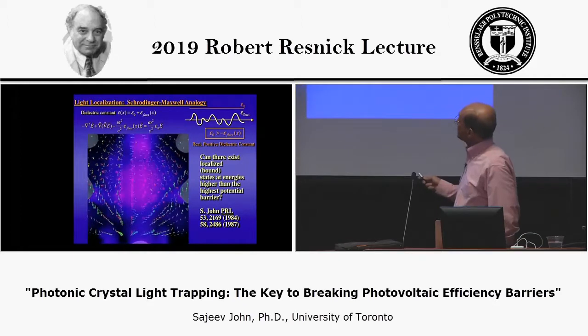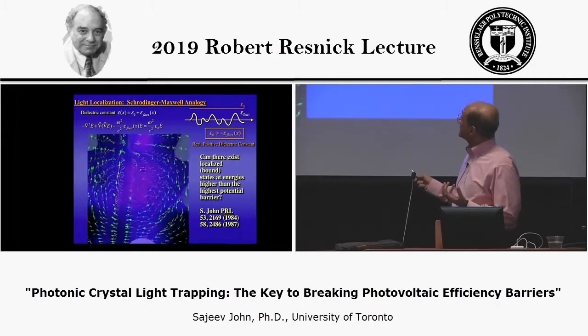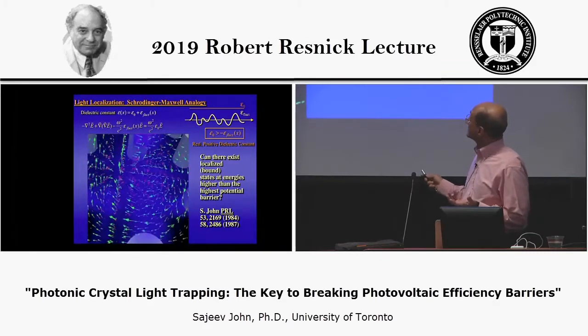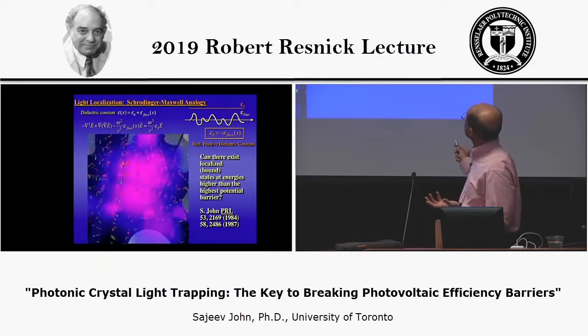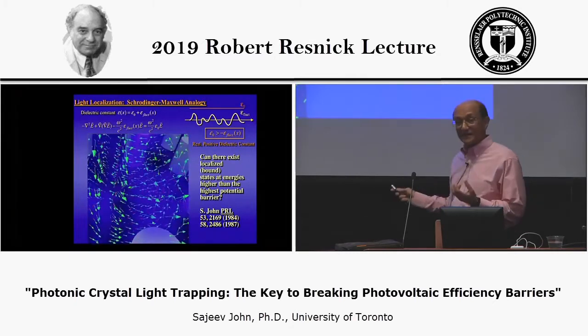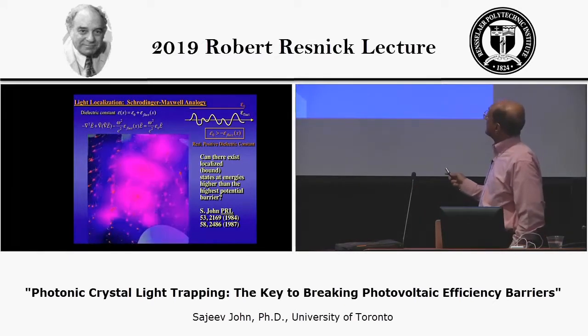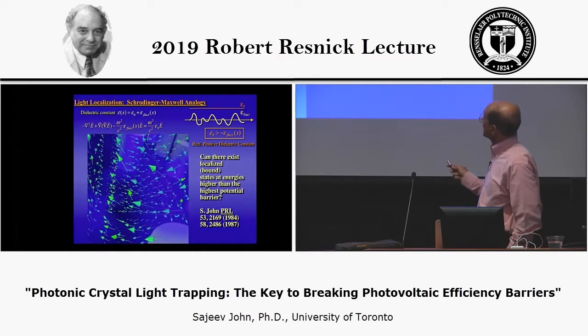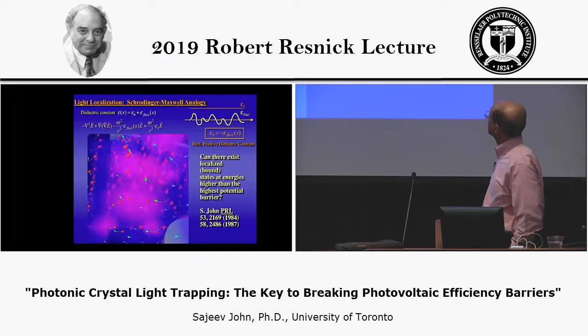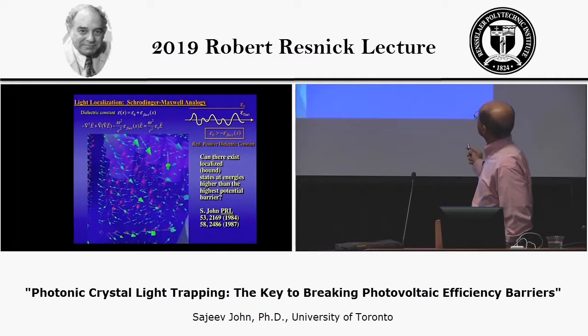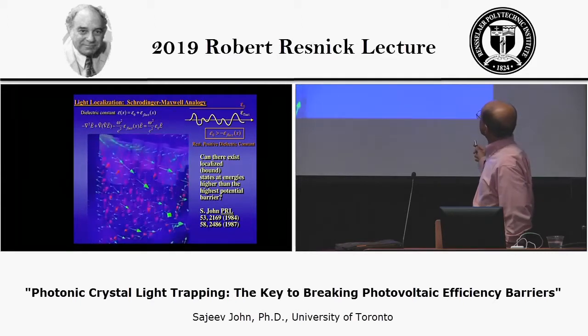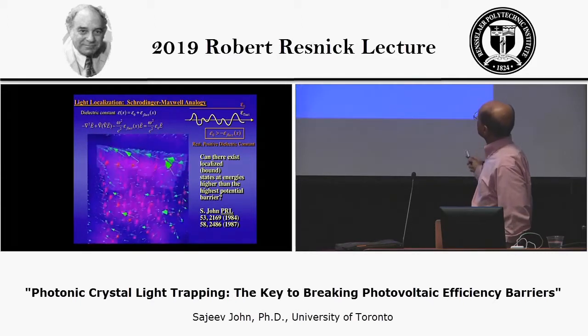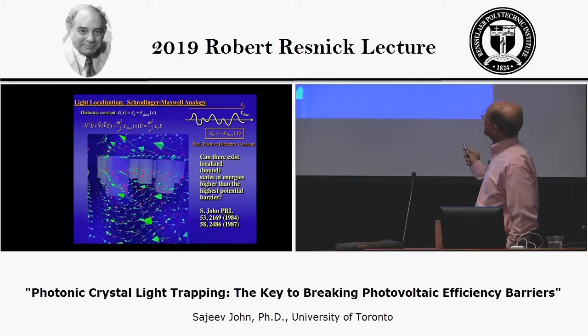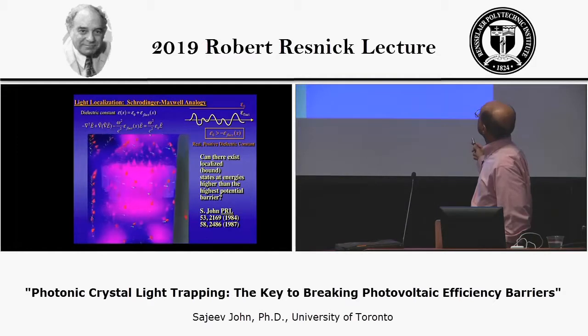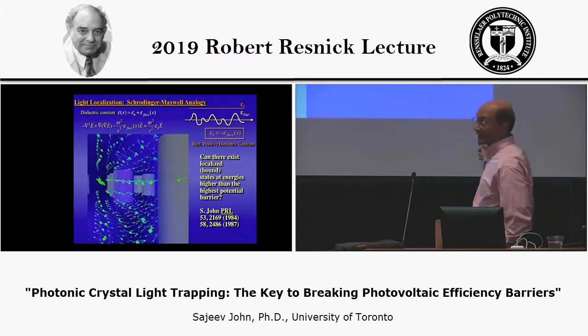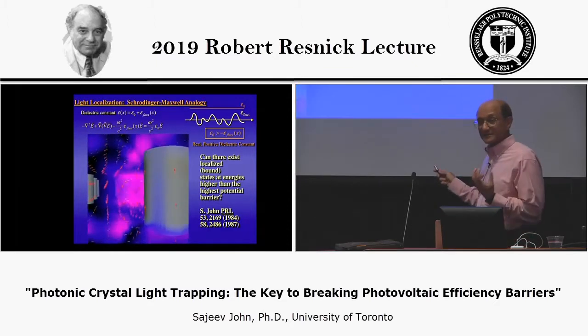And what I've done here is to write down the electromagnetic wave equation in a form that looks as close as possible to Schrödinger's equation, where the spatially varying part of the dielectric constant in this case is the analog of a potential in Schrödinger's equation, and the average part of the dielectric multiplied by the square of the frequency is like an energy eigenvalue. And if you're dealing with a real positive dielectric constant where epsilon 0 is greater than the maximum value of the fluctuating part, this would require that a bound state, if it were to exist, would occur within the positive energy spectrum above the highest of the highest potential barriers. So that's what makes this a difficult problem.